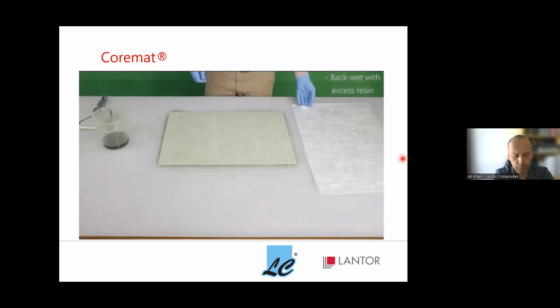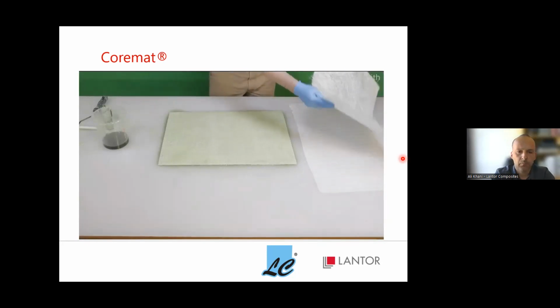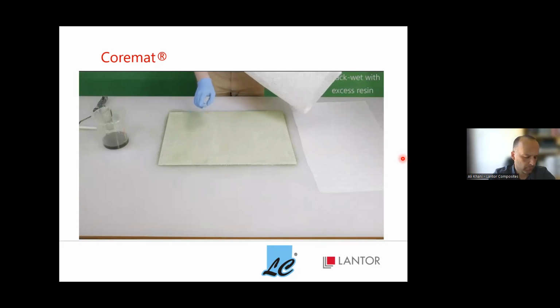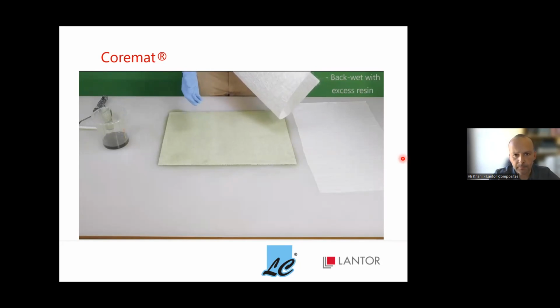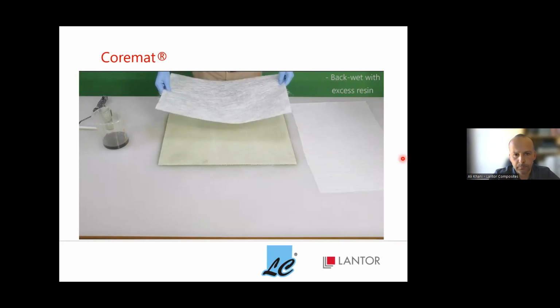We apply the second layer of glass fiber to the backside of our panel on the still wet core mat. Do not allow the resin in the core mat to cure when there's still excess on top. Instead, always laminate a thin layer of glass fiber on top and peel ply as needed. Core mat is a core material, and by far the best results in panel strength and durability are obtained when the core mat is laminated in the middle between fiber reinforcement layers.